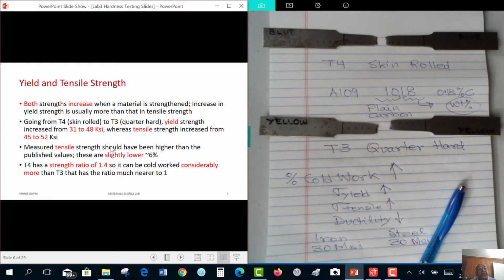Now, our measured tensile strength should have been higher than the published values. So if you read your specifications carefully, these yield strength and tensile strength are typically minimum values unless otherwise specified. So the manufacturer says that these are the minimum values you can expect from our materials, and they publish this. So often, other than the ASTM standard, you should really be looking at where did you buy this material from and what were their material specs. That is what we really should be comparing to.